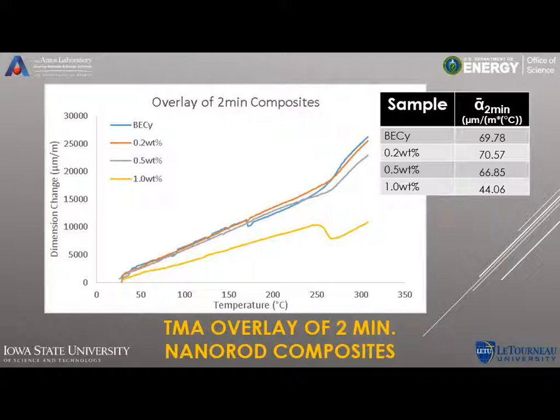And that, I think, is just an outlier data line, because you can see that the graph itself has this downward slope and then upward. And so that may be due to the sample slipping beneath the probe, because that's not the sort of graph that you should get. And so this data for the 2-minute set was a little bit more unreliable, just because of that deviance in the data for the 1.0%.